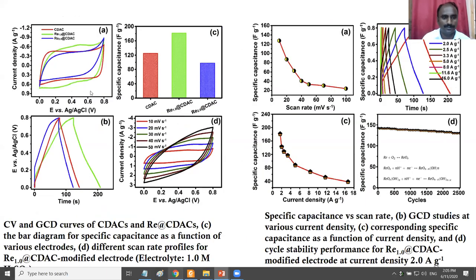This is the capacitance application. In the same way, we need to measure the CV. You can see the rectangular CV profile. It indicates an open potential window for energy storage application. The bare carbon has a capacitance of nearly 120, and for rhenium doped at different ratios, 1 weight percentage and 2 weight percentage, the rhenium 1 weight percentage is higher than rhenium 2%, because of the higher loading of rhenium.